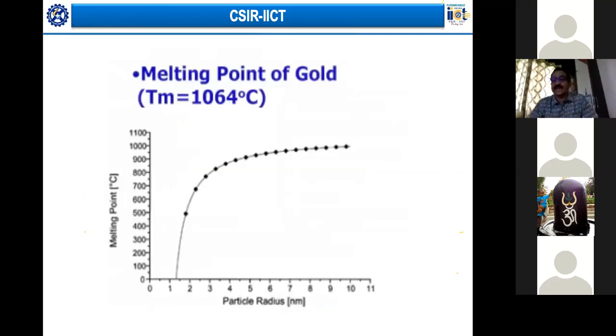Let us look at one example, the melting point of gold. It is generally about 1000 degrees that normal bulk gold material melts. But as you see, as there is a decrease in the particle size, the temperature also comes down. For example, gold nanoparticles of about 1 to 2 nanometers melt at around 500, which is about 50% less temperature. So there is 1000, and as the size decreases, the melting point comes down to about 500 degrees centigrade.